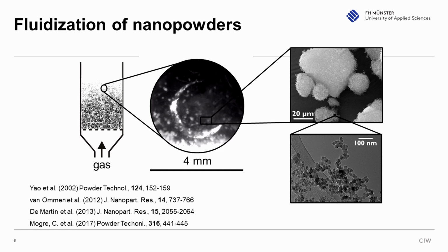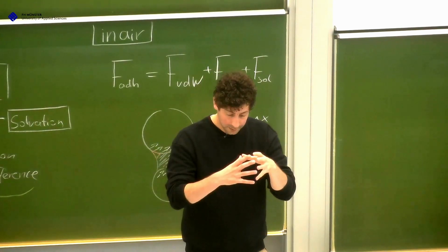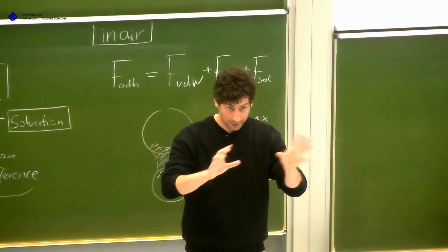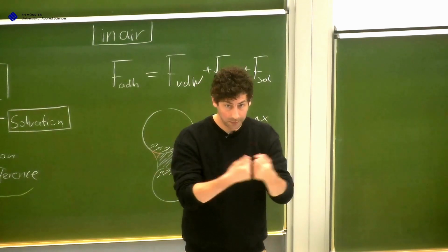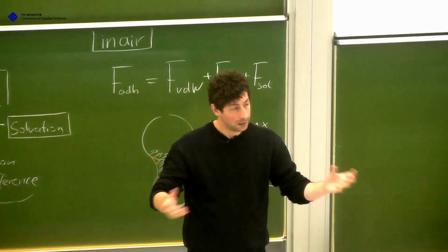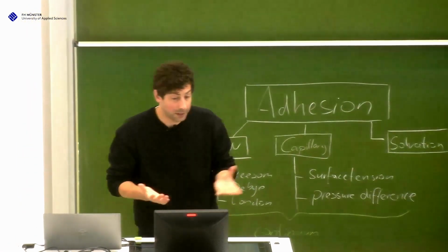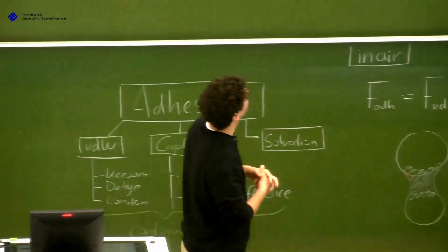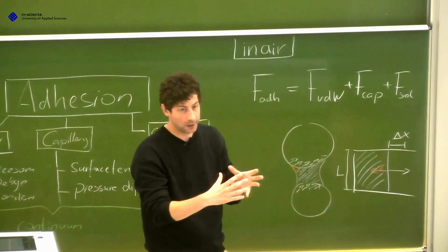millimeter flying around. And at this time, and this is also what I investigate, I say that the size of the agglomerate is not static. And all the time, the agglomerates coagulate because they meet some other particles and then they grow. But also there is stress from the fluid and from the impact, so they also detach. And we have one publication, and I think it's the only publication investigating this, that's quite weird, where we showed that the size of the agglomerates over time changes, and also the porosity over time changes. Yeah?